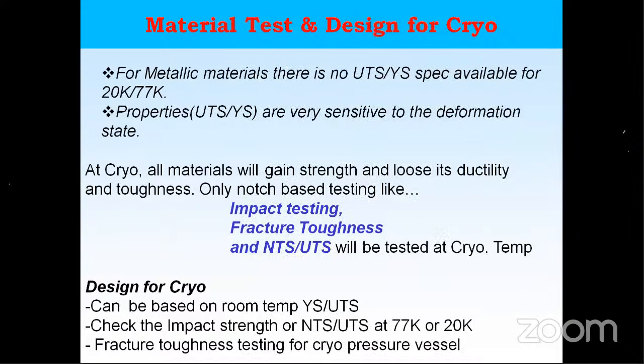Then for low temperature, this is my view. I have already made most of the cryogenic materials for ISRO. My view is that for metallic materials there is no UTS and YS specification. If you see any standard AMS specification, there is no such specification, because when I test a specimen at room temperature of any material, I mean steels, of course I'm discussing steels, I get a very consistent value at ambient temperature.